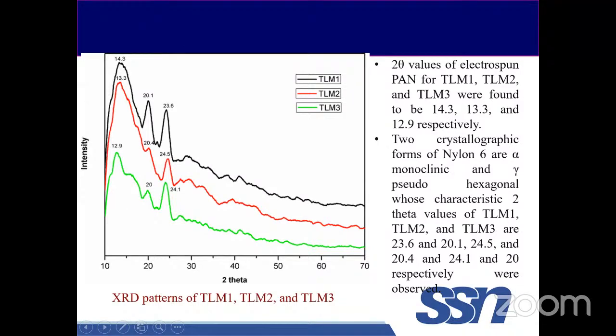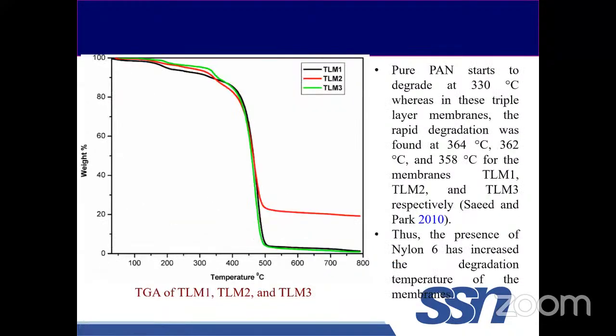Then we studied the thermogravimetric analysis of the prepared layer membranes. For pure PAN, the degradation starts at 330 degrees Celsius, whereas when we blend nylon and PAN, the degradation temperature increases further from 330 to 364, 362 and 358. The increase in degradation temperature is due to an increase in the content of nylon, right?